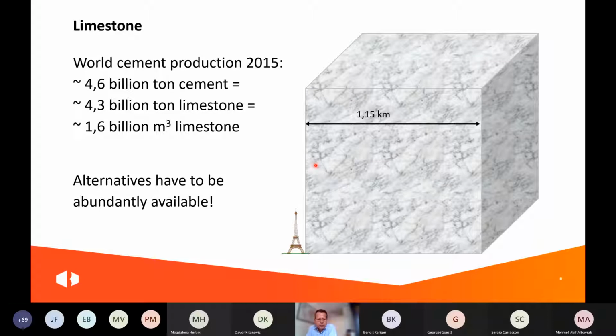For concrete we need a lot of material. Cement is mainly produced from limestone and a bit of clay, but mainly limestone. And here you see what we need of limestone every year. It's more than a cubic kilometer of limestone we need, and you see the Eiffel Tower next to it, and this is on scale. So if we search for alternatives for cement, it's clear we need a lot of alternative material as well. And for concrete, of course, we need 6 times as much as this for the aggregates. So alternatives have to be abundantly available to consider them.